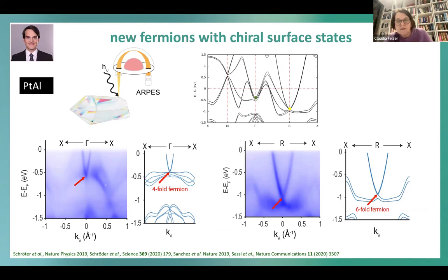So simply to compare the calculation again with the experimental results. On the left side, we see the fourfold fermions. You see always the calculation versus the blue pictures, always the experimental data, the upper ones.